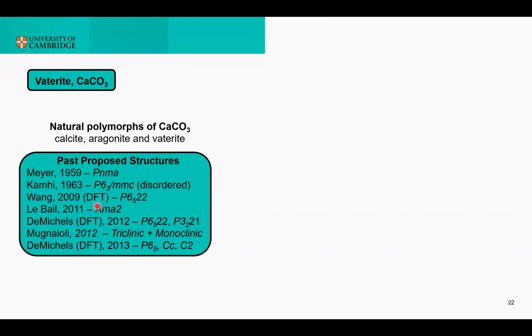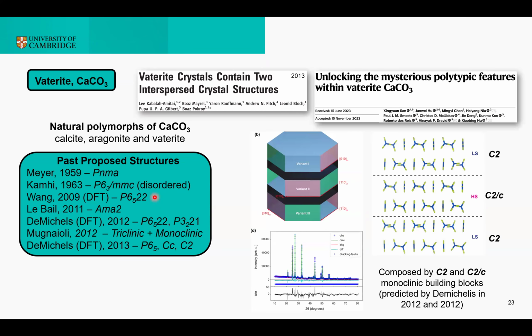Nonetheless, whether the structure was solved remained actually an open debate. Only very recently, first in 2013 and then in 2023, it was recognized that the experimental powder diffraction data could not be described by one structure only. It seems clear that vaterite was in reality a polytypic structure, a structure that basically contains crystalline domains which are not periodically consistent along one direction, particularly one of the stacking directions.